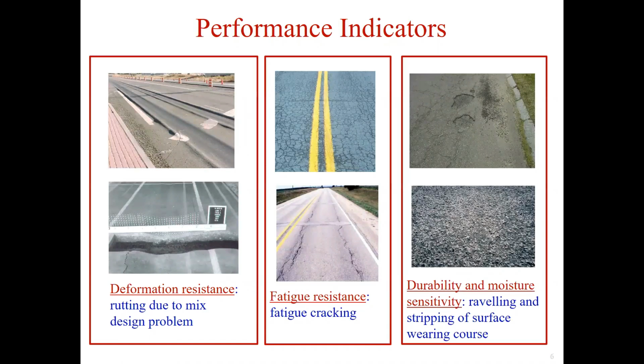Now let's go back to see these performance indicators and corresponding distress. If there's no sufficient deformation resistance, then rutting would occur, which shows the surface depression in the wheel path. One of the main reasons of rutting is improper mix design or manufacture, for example, excessively high asphalt content, excessive mineral filler, or insufficient amount of angular aggregate particles.